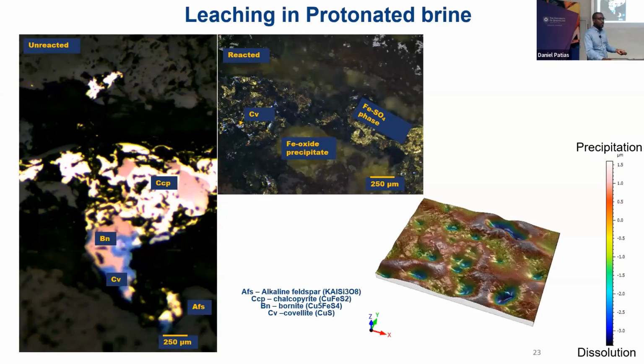In the solution we proposed, which is the lixiviant we proposed, that was a different case. So at the end of the leaching, we observed so many phases forming, and the texture is not really nice as we saw before. But the good news here is that we're getting copper from both chalcopyrite and bornite.